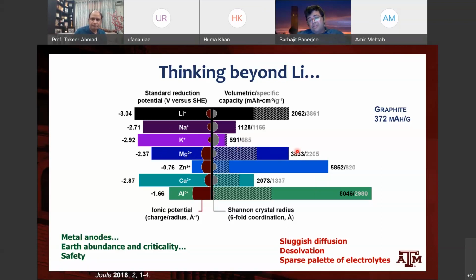And then the other idea is that we've struggled so much with trying to work with lithium metal anodes, because of the large propensity for dendrite formation. Is it possible by moving to magnesium or perhaps calcium that we can actually use metal anodes and come close to realizing these theoretical capacities, but without these same challenges of dendrite formation? So this remains a great thing.